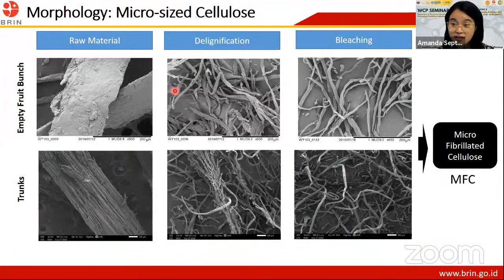So this is the morphology of the micro-size cellulose. For example, the empty fruit bunch raw material is quite different compared to the oil palm trunks, where you can see distinctive microfibrils attached on it. But then after the delignification, the morphology is quite similar, where you can see the microfibrils start to get loose from the bigger bundles of fibrils. And then after the bleaching, we can get totally individual microfibrillated cellulose, or MFC.